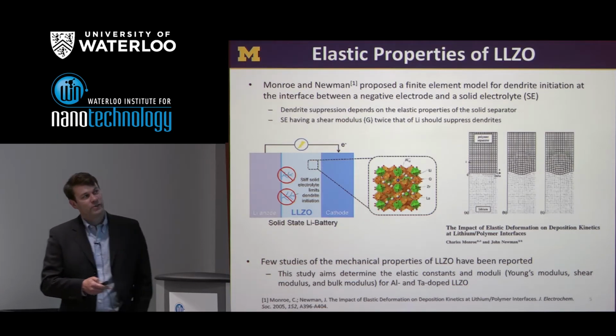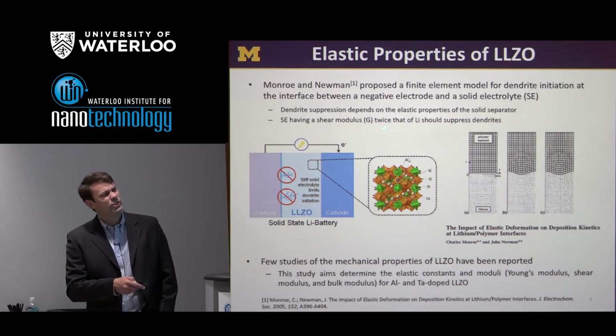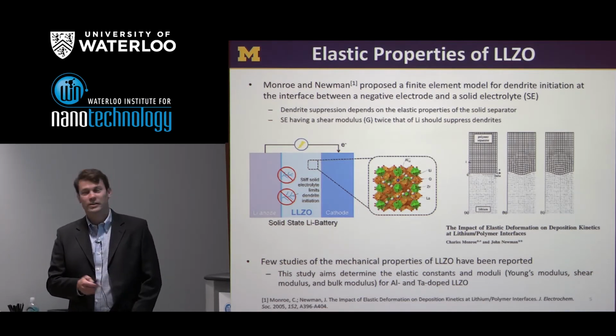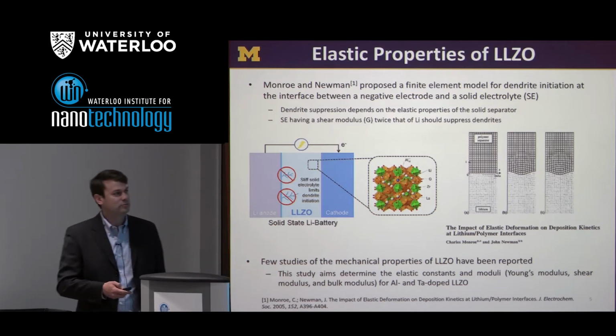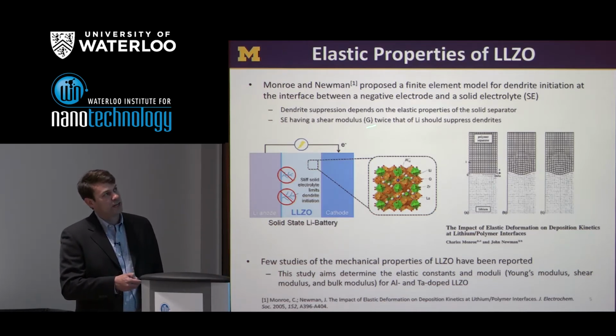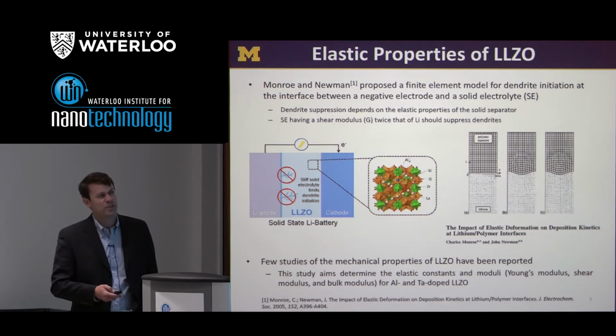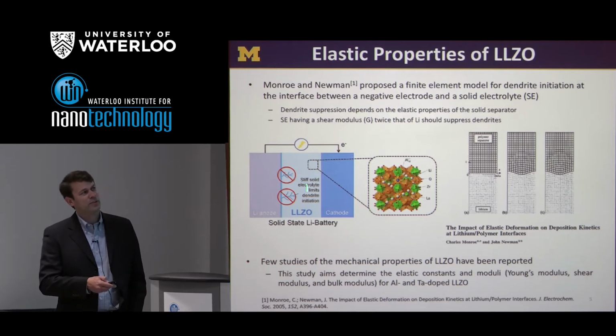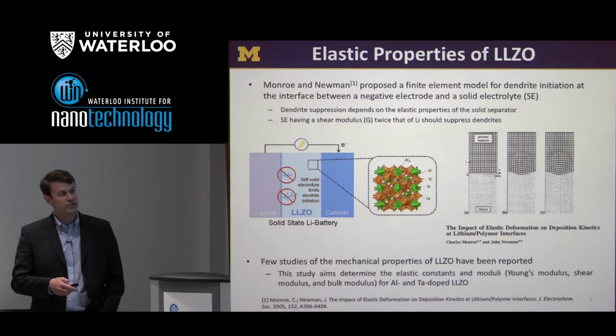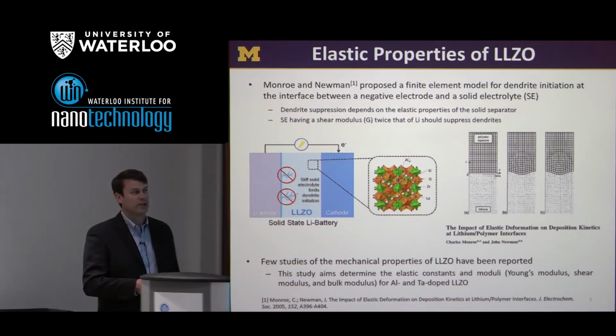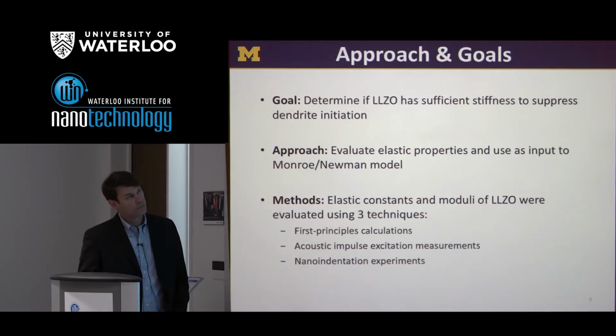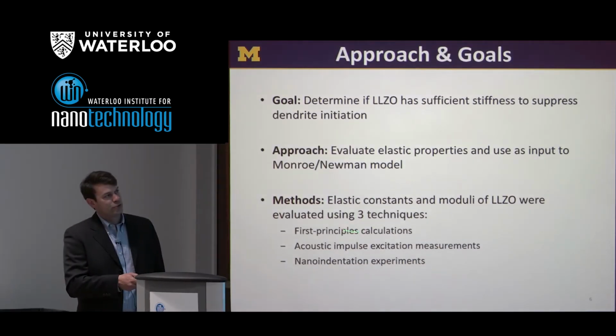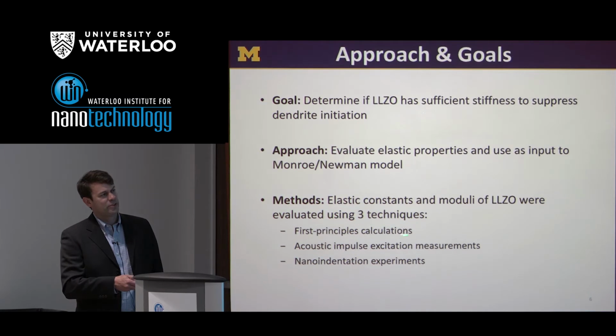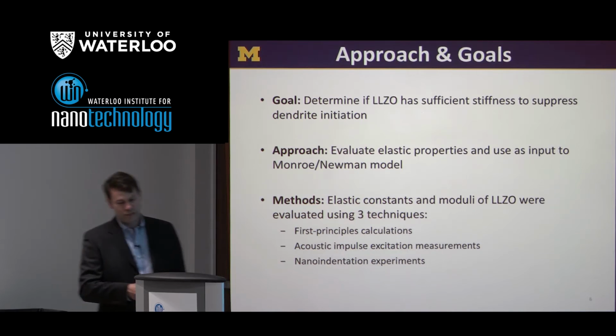Their model suggested that if you had a solid electrolyte with a shear modulus G which is twice that of lithium metal, then you had some hope of suppressing dendrites. So we set out to measure the shear modulus and basically all the elastic properties of LLZO, in hopes of comparing with the elastic properties of lithium to see if LLZO could satisfy this criterion. This is a combination of first principles calculations, which I'll of course tell you the details of in a moment, but also some experimental work using acoustic impulse excitation and nano indentation experiments done by some of our experimental collaborators.